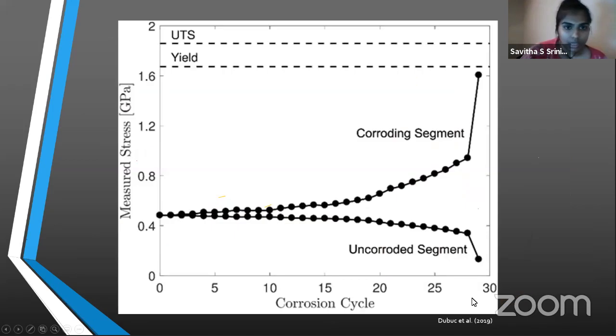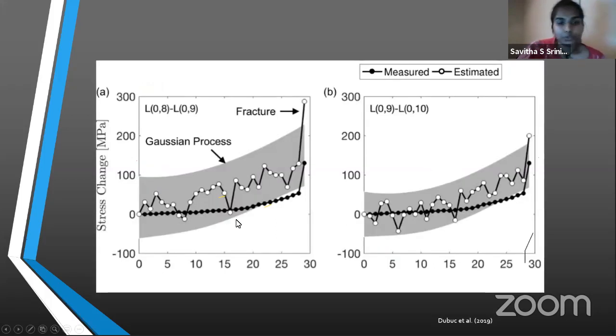What we see here is the change in stress of the uncorroded and a corroded strand. You can see that the stress in the corroded strand keeps increasing till it actually reaches the fracture point, while the uncorroded strand really doesn't have that behavior. This also shows the comparison of the actual measured stress using stress and strain, and the stress that's estimated using the ultrasonic pulse velocity. The white dots are the estimated values and the black dots are the measured values. With a statistical analysis at a 95% confidence level, it does have a similar trend to the measured stress values. So it does show that you can use ultrasonic pulse velocity to gauge the extent of corrosion in pre-stressing strands.